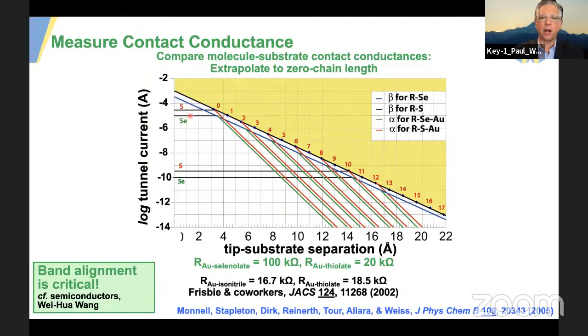That was the result. And so the bad news was that if you give me a contact material, I can't just tell you what to use. But the good news is we can tune that band alignment and optimize it by choosing a backbone or functionalizing that backbone to shift the bands on one side or another.